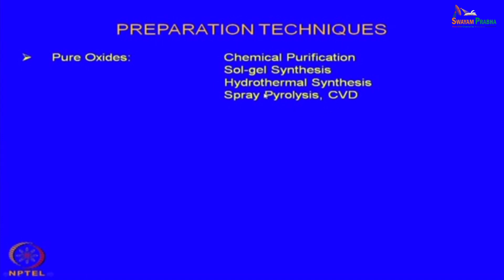By that process also you can crystallize very fine oxides within the liquid environment, okay, or some kind of a liquid process. Okay. Then there are two processes called spray pyrolysis and CVD. CVD is a short form of chemical vapor deposition. Normally CVD is also another technique by which one can make fine powders. Spray pyrolysis, you take, again, a solution and spray it, sprinkle it inside a hot chamber or in a flame, so that the droplets immediately get decomposed in the hot environment and produce the solid particles which are very fine.